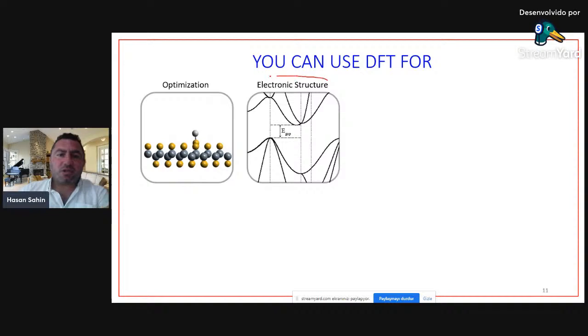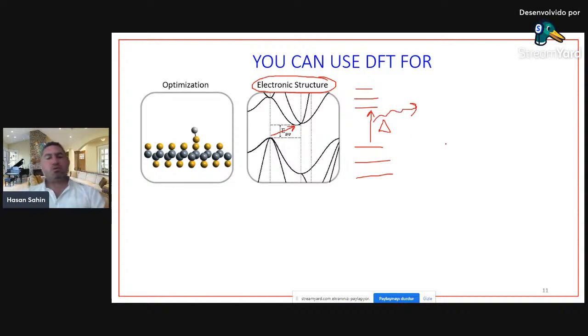It is electronic structure. You can calculate whether your crystal structure is a semiconductor, an insulator, or a metal. For example, in this case, after calculation, we find that we have an indirect bandgap semiconductor. And it doesn't have to be a crystal structure. By performing electronic structure calculations, you could obtain molecular orbitals, and you could say this is the HOMO-LUMO bandgap, which is delta, and this bandgap is very important because of some emission properties. So maybe you can be interested in this gap. You can calculate the electronic structure of molecular structures or crystalline structures. It doesn't matter. DFT allows you to do it.